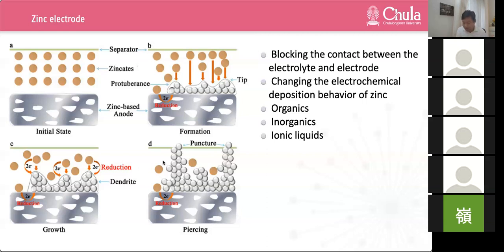The introduction of organic and inorganic additives to the electrode and electrolyte can inhibit zinc dendrites by changing the electrochemical deposition behavior of zinc in the electrolyte. Recently, some organic agents have been added to the electrolyte to deposit a flat zinc-based film composed of small grains by influencing the electrochemical properties of zinc electrodes during electrodeposition, such as the grain size, chemical composition, and anti-corrosion property.